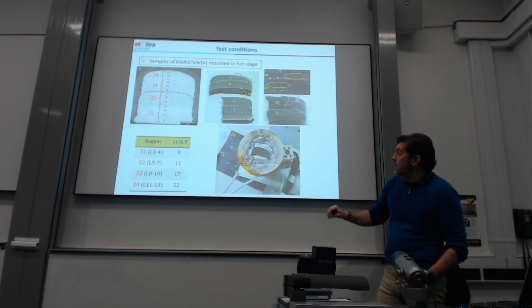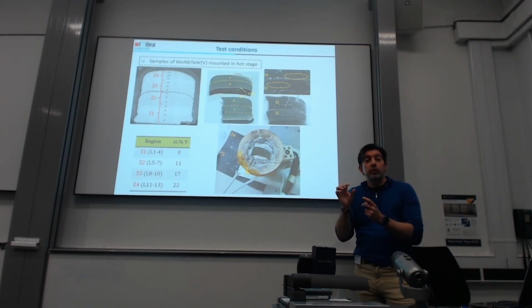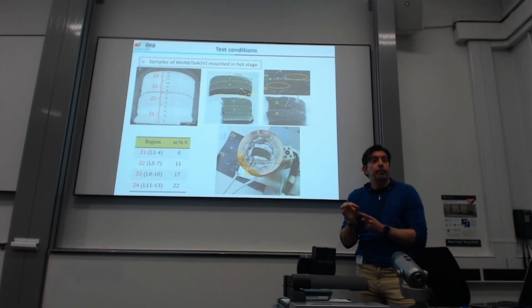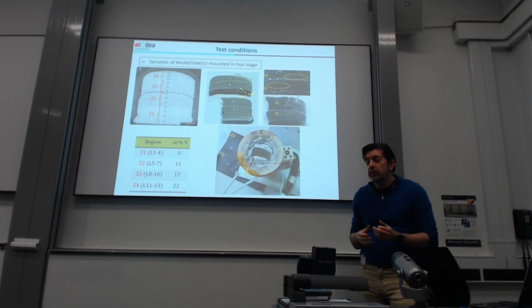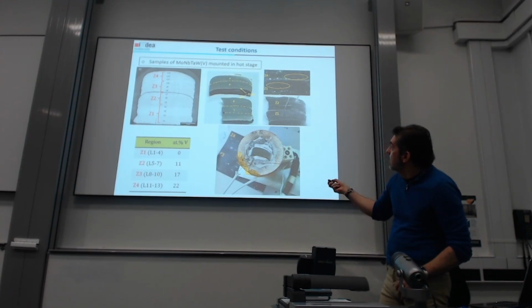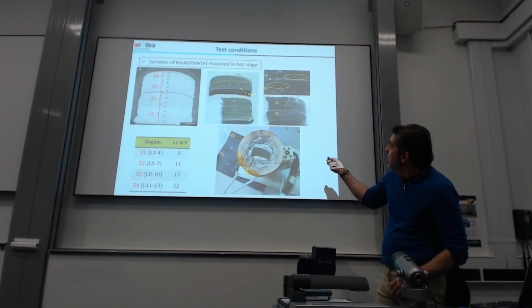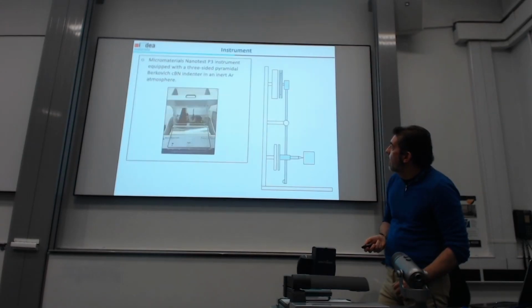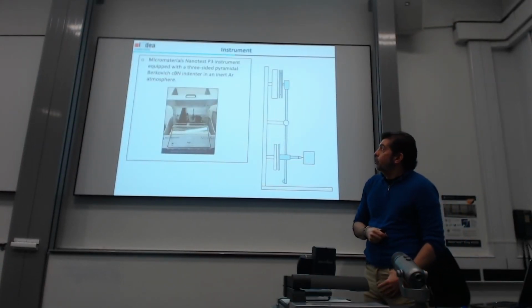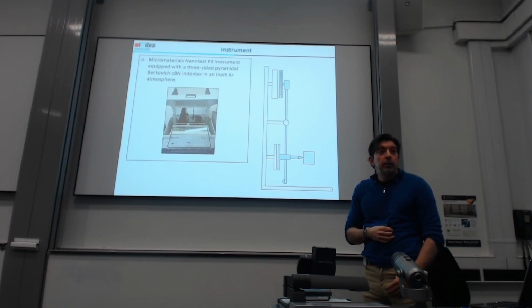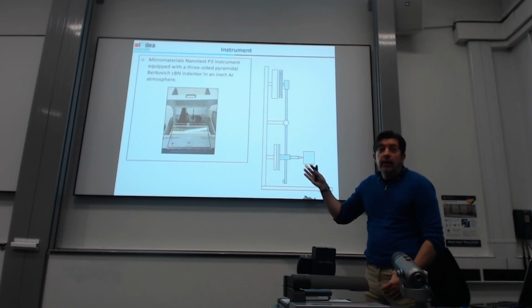We get these pieces. This is the piece mounted with high temperature cement on the hot stage. Again, you can accommodate large samples. It's placed, so I look at this. There are also already some indents here. And I also used the same platform with a cubic boron nitride indenter tip, in an inert gas atmosphere.